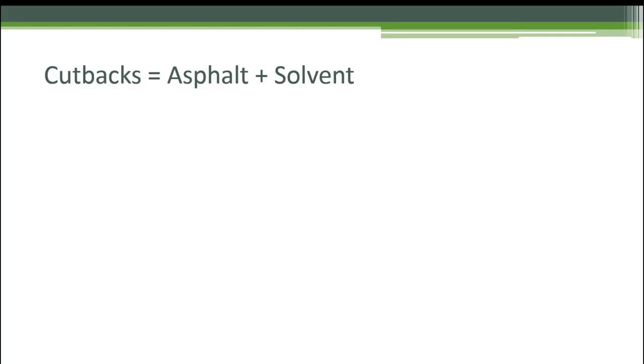Well, how do you do that when you have a thermoplastic material? You got to lower the viscosity. You got to get it to flow at ambient temperature, at room temperatures. And how do you do that? You use cutback asphalts. And all a cutback asphalt is, is asphalt residual plus a solvent, some type of basically petroleum solvent. So you can think about it when you get to specifications as cutbacks cure. And what you're interested in is getting that residual asphalt in place. The solvent is just a way to deliver it. What happens to the solvent? It evaporates, leaving the residual asphalt in place. So you can think about it as cutbacks cure.